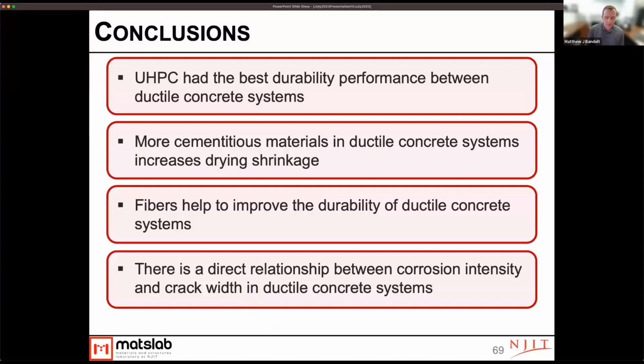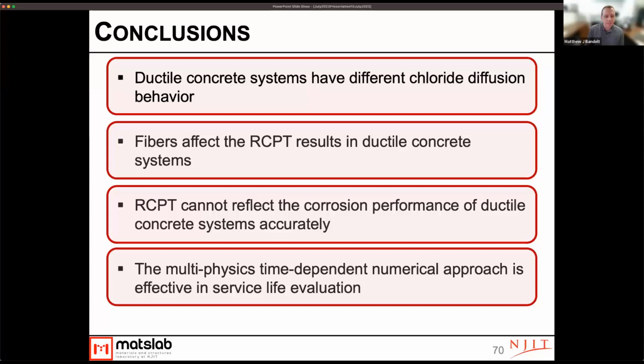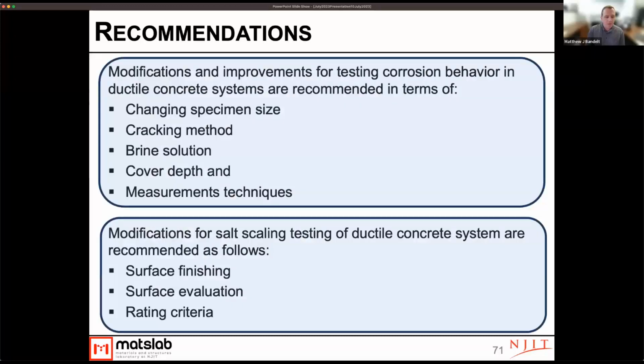And we obviously saw a direct relationship between corrosion intensity and crack width in the ductile concrete systems. Another big thing that came out of this study was some of the considerations one must take when using some of these newer concrete materials and the test methods that go along with them. For example, we saw how the fibers influenced RCPT results, and why those might not be the best test method. Matt had also gone into some issues with salt scaling, et cetera. And our multi-physics numerical approach gave us some interesting information on service life performance as well. So there are lots of different recommendations that we have.